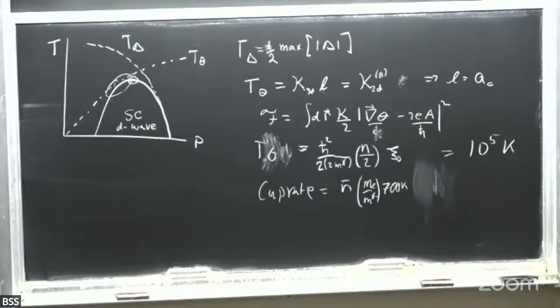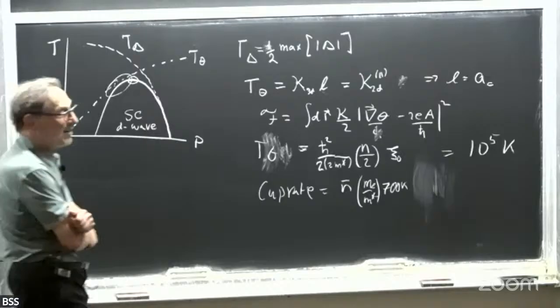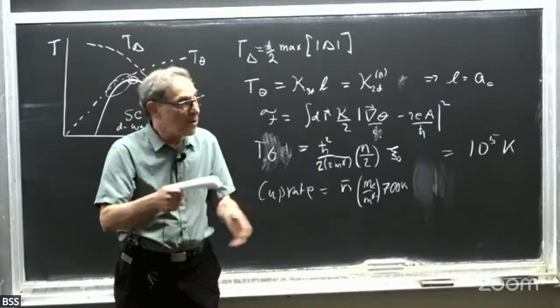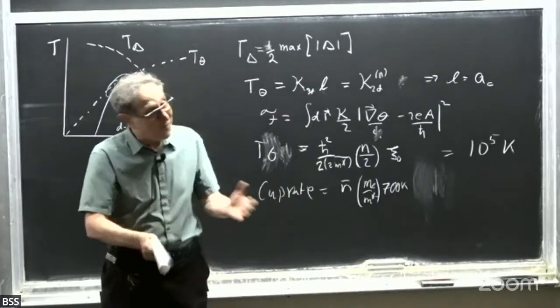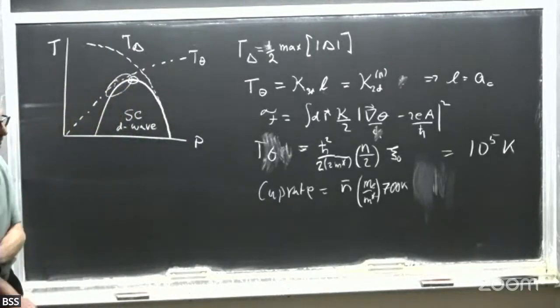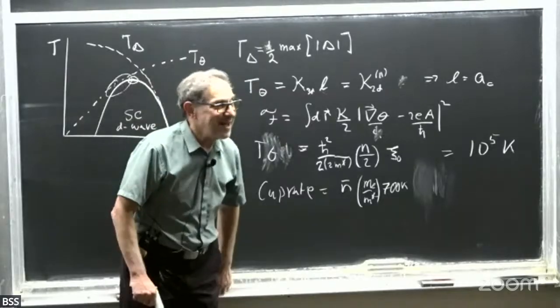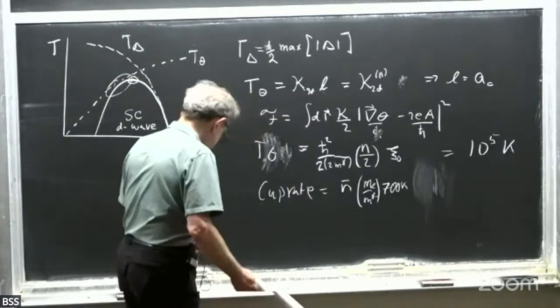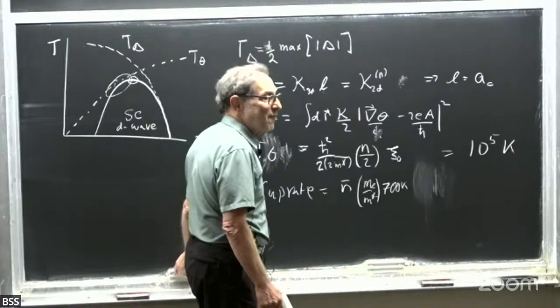specific heat. In fact, I think that data may have the largest range of reduced temperatures in which critical scaling is seen of any critical point in a solid. You know, solids are bad for critical phenomena. You always have disorder and inhomogeneities and strains. It's very hard to get very close into Tc. I think they rarely go for more than one decade of reduced temperature, and this goes for two.